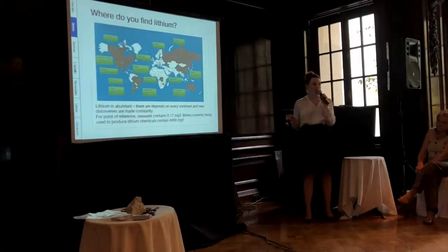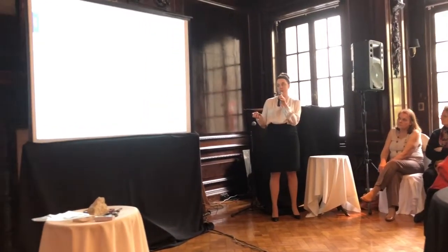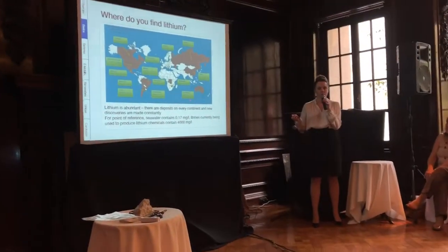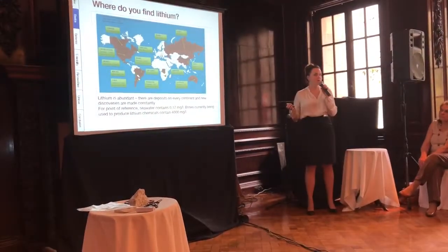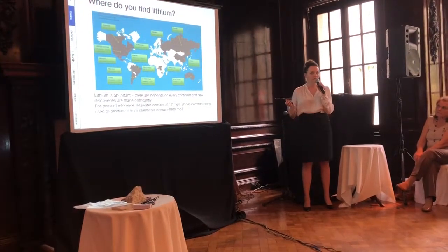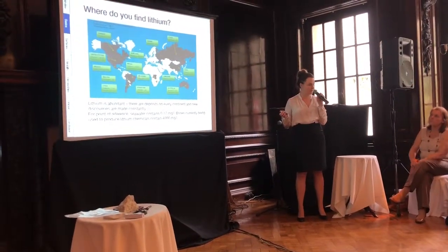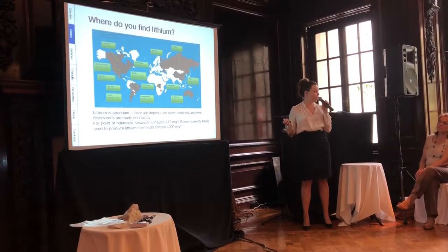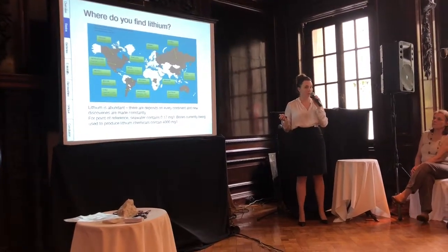And for a point of reference, seawater itself contains 0.17 milligrams of lithium per liter. The brines that we're going to talk about later that are used in Argentina to extract lithium contain 4,000 milligrams per liter. So there's a major difference, but it's important, if someone says, oh, there's a lithium deposit, to get an idea of how it stacks up against other lithium deposits in the world, to see if it could ever be economically viable to use for lithium extraction.